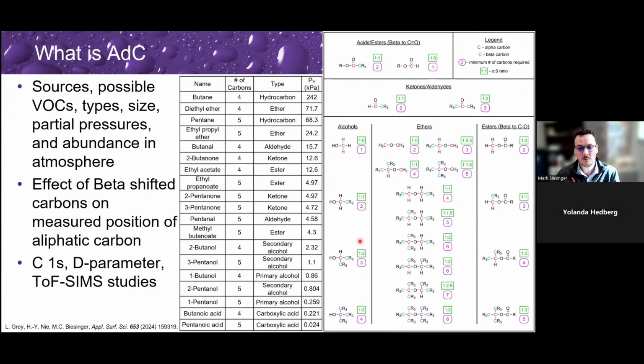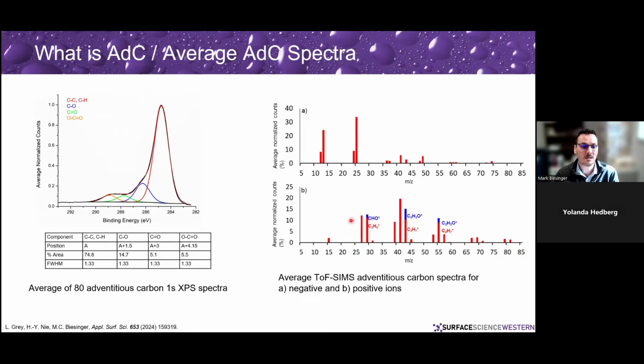If we take those sorts of things into account, well, first we also looked at what the adventitious carbon looks like. We did a whole bunch of averaging of different spectra. This is what an average of 80 adventitious carbon spectra looks like. It's carbon with some carbon bound to oxygen, generally around 25% carbon functionality bound to oxygen.